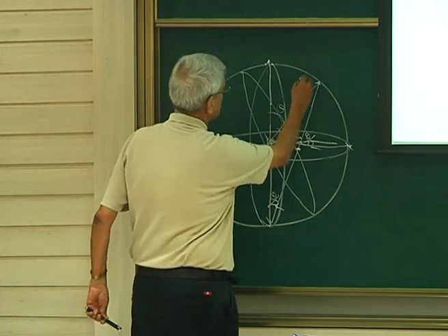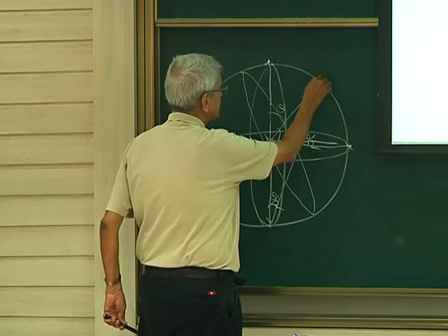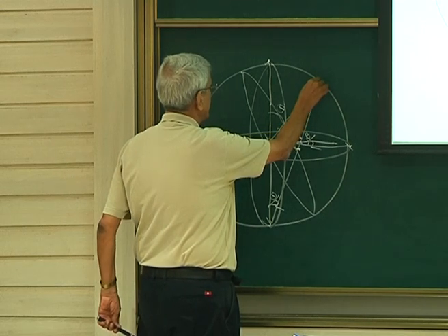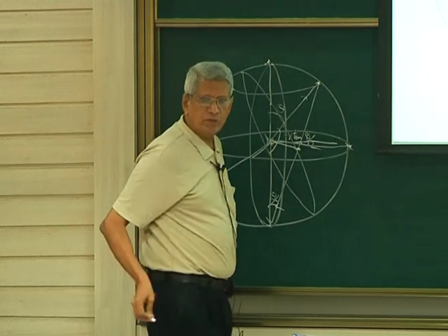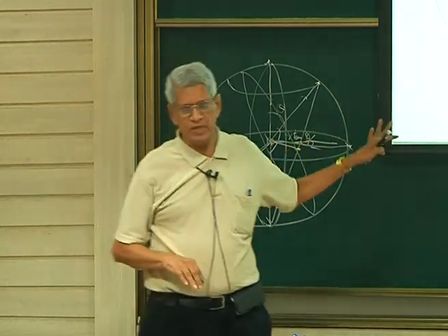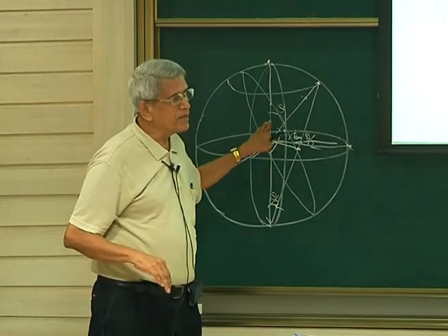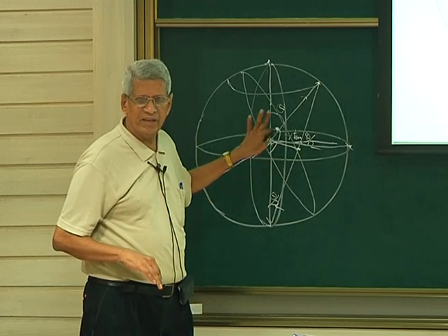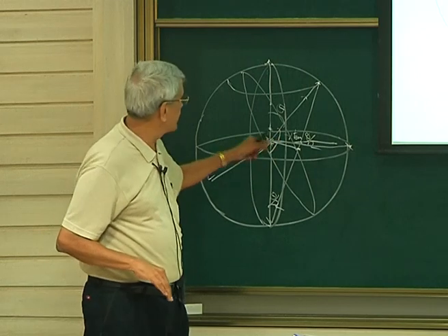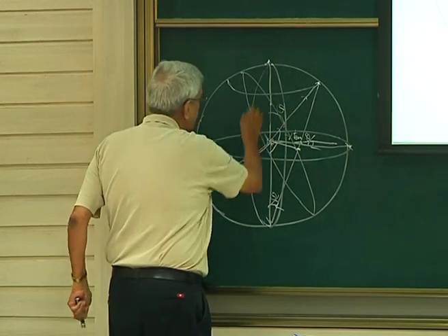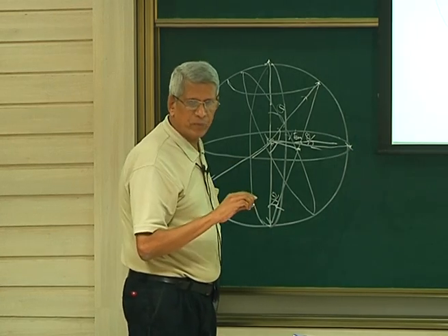Then another important aspect is, suppose this point is there, all the points on the surface of the sphere which are making equal angle with respect to this, okay. If you try to do that, that projection on this surface is also going to be a circle. That is another property of the stereographic projection, okay. Essentially what is going to happen is that this projection will be there, and all these will come as an arc of a great circle, okay.